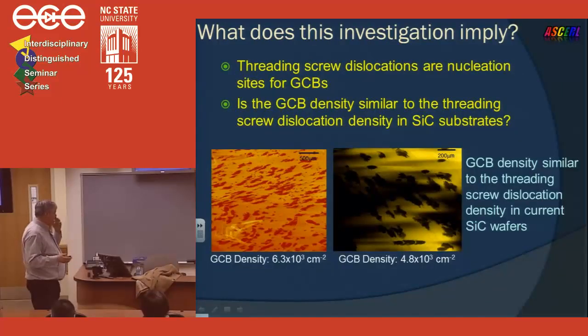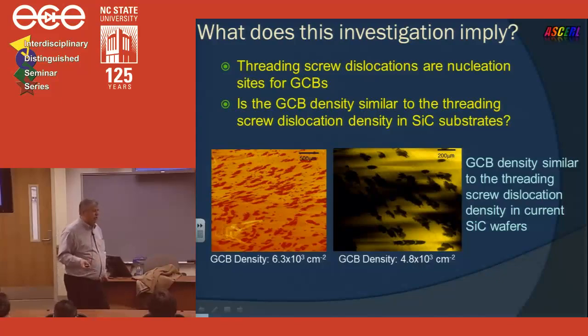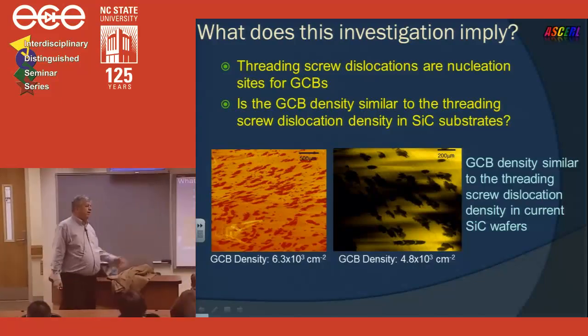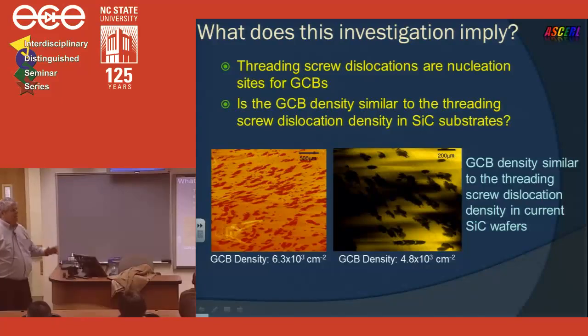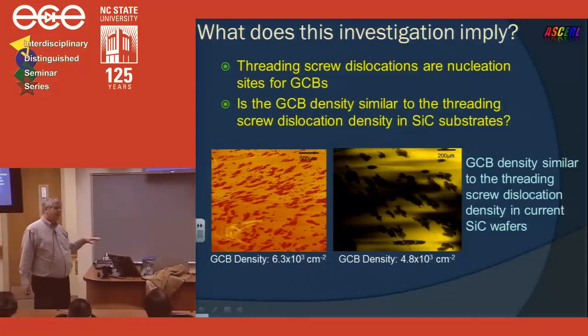Okay, so now the next question is, all right, Kurt, you told me that the screw dislocations, but is the number a correct density? High quality silicon carbide substrates do indeed, people have measured threading screw dislocation densities on the order of 5 times 10 to the third per square centimeter. And that's the typical state-of-the-art stuff that you could buy. And for these samples that I just showed you here, we just took a snapshot, counted up, and we got a number about 5 times 10 to the third. So roughly speaking, every screw dislocation in the bulk silicon carbide crystal is a nucleation site for the growth of graphene.